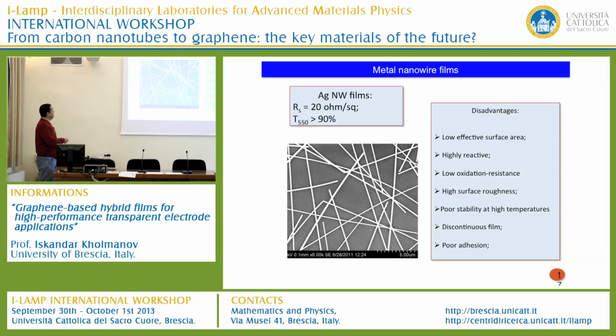First of all, the electrical conductivity of nanowire films is provided by the percolated network of nanowires, while the optical transmittance is provided by the open spaces between nanowires. So this kind of film has very low effective surface area, because the optically transparent area is not electrically conductive, and the electrically conductive area is not optically transparent. If you use this kind of nanostructure as a transparent conductive film in solar cells, for example, the efficiency of the solar cell might be very low because of this non-effective surface area.